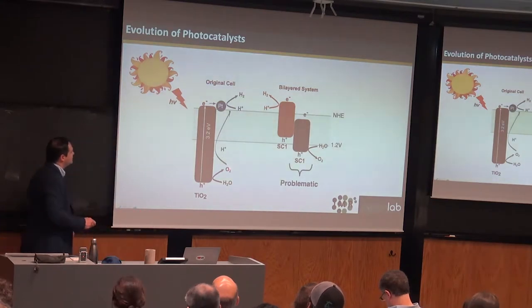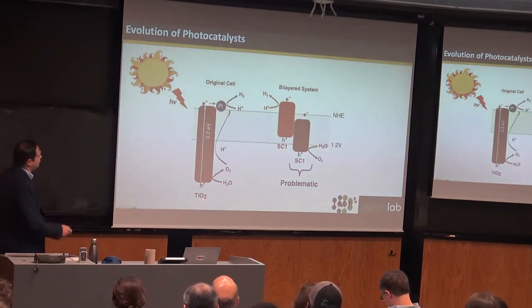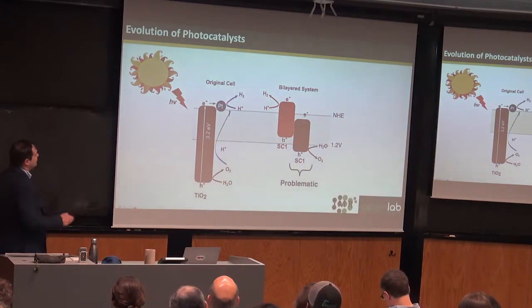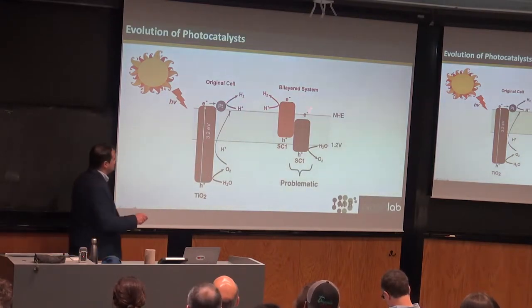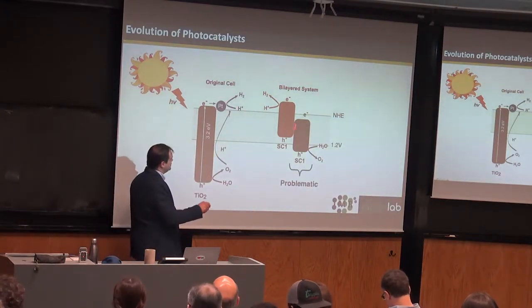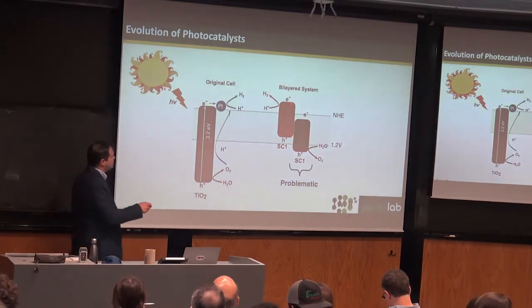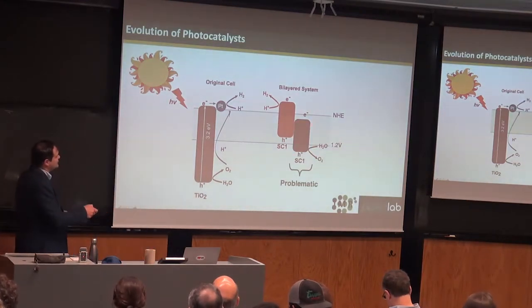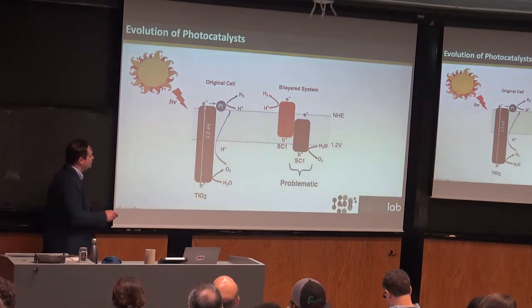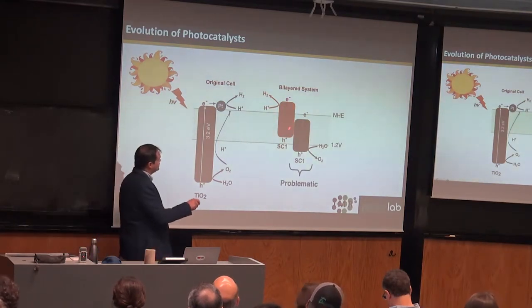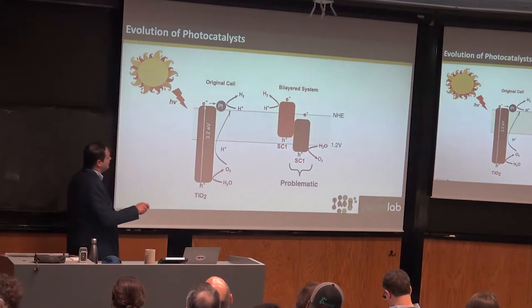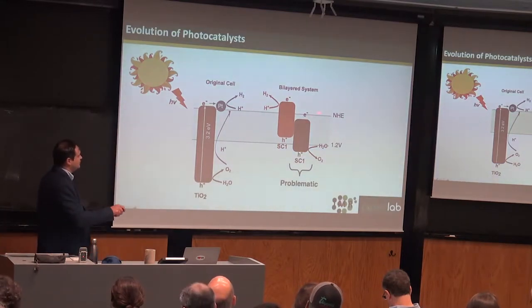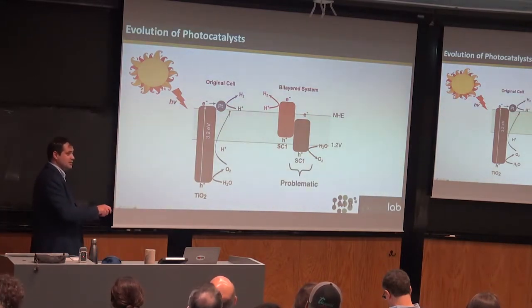And so the idea is to go from this original idea of a wide band gap semiconductor and platinum to a case where now we consider using the interface to charge separate carriers generated in these layers, in these semiconductors, and then use those semiconductors either by themselves, bare, or with a co-catalyst, like platinum, for instance, to essentially drive the photocatalysis. And of the two, this is the vexing problematic one.